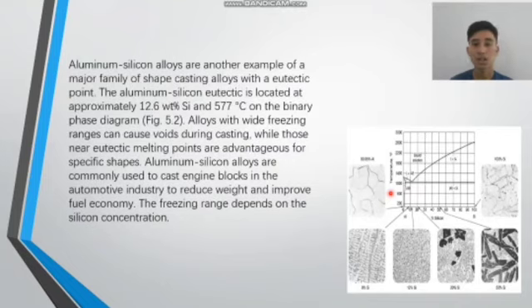aluminium silicon alloys are another example of a major family of casting alloys with a eutectic point. The aluminum silicon eutectic is located at approximately 12.6 wt% Si and 577 degrees Celsius on the binary phase diagram, picture 5.2. Alloys with a wide freezing range can cause faults during casting, while those near the eutectic point are advantageous for specific shapes. Aluminium silicon alloys are commonly used to cast engine blocks in the automotive industry to reduce weight and improve fuel economy. The freezing range depends on the silicon concentration. Okay, next.